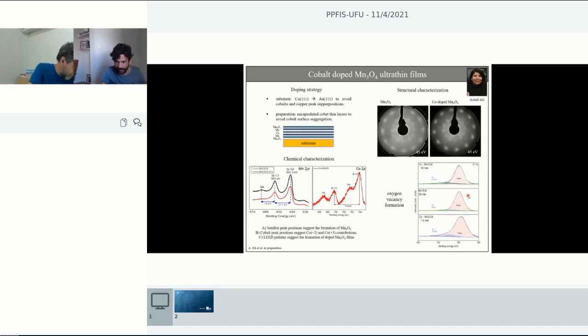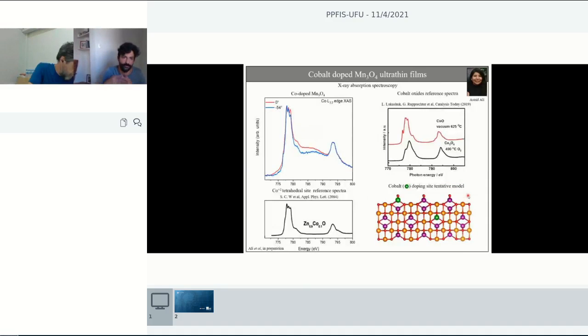And then we can add to this many other analyses about the vacancies formation. We performed a lot of experiments at the synchrotron as well, using X-ray absorption spectroscopy, where we can see signatures when you take this kind of X-ray absorption spectra at different angles that reveal more the bulk and the surface contribution. And then when we compare this with what we know from the literature for cobalt oxides that we would like to avoid, and for some examples of cobalt doping zinc oxide materials, we find a lot of correlation.